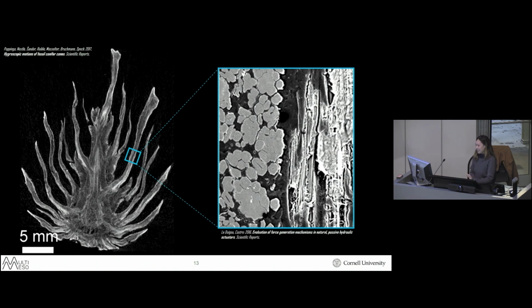So now taking a closer look at the material structure of the pine cone, we can see how the cellulose microfibrils are arranged in two directional layers. And this bilayer structure is what causes the pine cone to swell or shrink in response to moisture changes.